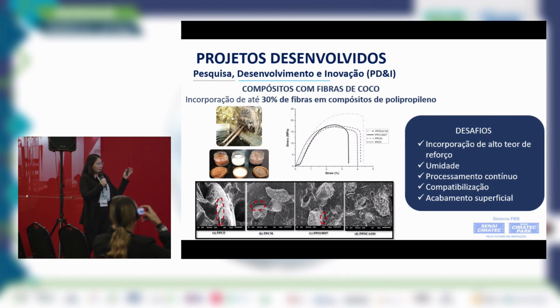strength results. I'm not going to drill down, but when we compare the four images, we can see the voids in the first three ones and a low level of interaction between the polymer and the fibers in the first three. We highlight that in red. The interface is not so good between both materials, but in the last image, we used a compatibility agent. So we improved the interaction on the interface, fiber and polymer.